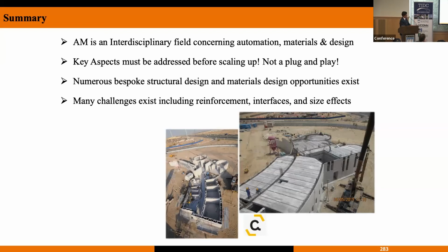To me, the whole point of additive manufacturing is not to do conventional construction, unless you're really going to be cost competitive because of the removal of the formwork. That again still is not an opportunistic way of thinking about the design. Concrete, for as long as we know it, pretty much does not have a mechanism that prevents propagation of a crack other than crack bridging and the things that happen in typical concrete as a composite in terms of having aggregates. Concrete is a composite material in itself, but it only has so much toughening mechanism to prevent the crack. There is an opportunity for us to design a material without changing the composition. So the material is still the same. Just by controlling the material architecture, you can improve the response without adding a cost, but indeed by reducing the cost because you're removing the formwork.